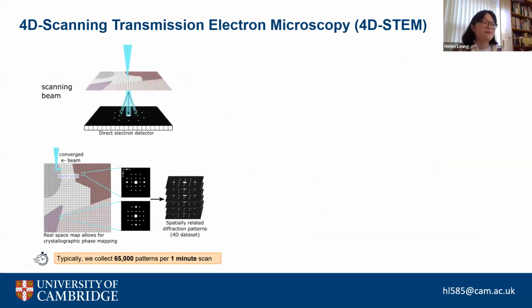Okay, so 4D STEM, scanning transmission electron microscopy, is slightly different to the 3D ED side, because this time we have a focused beam rather than a parallel beam. And so we're working with a convergence angle. In our case, we work with convergence angles of maybe 0.1 milliradians. The idea is you scan your beam across your sample, and at each real space position, you collect one reciprocal space, so one diffraction pattern. This gives you this 4D data set of spatially related diffraction patterns.